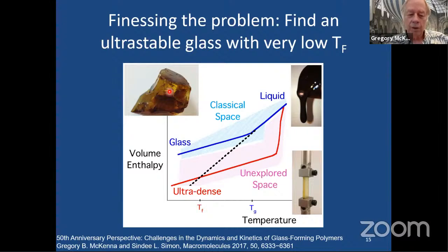And it's a good kind to get because it comes in big stones. When they get older, they come in much smaller pieces. And here's what it looks like after we've machined it. So we can actually do viscoelastic measurements. So we can measure the relaxation time through ideas of time temperature superposition of the material in this upper bound region. And I'm going to show that again as we go, because it's going to have a low fictive temperature. And we're going to be able to work in between the glass transition temperature and the fictive temperature.